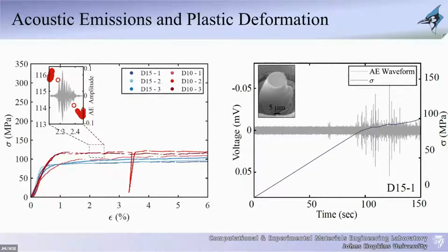So this is a burst. This is a burst of dislocation plasticity. And during that burst, you can actually see that there are multiple bursts happening internally that you would have never measured with the load displacement only. But with these acoustics, you're actually able to get a significant amount of further understanding of it.